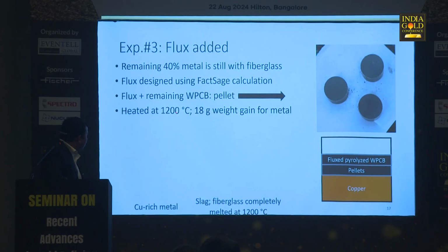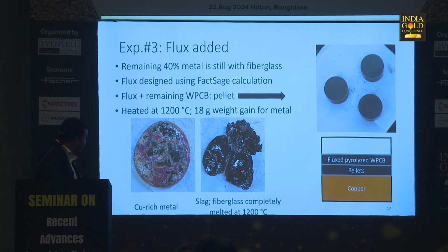Then we processed it at 1200 Celsius only, and after the experiment, you don't have any solid fiberglass left. So you have slag, you have metal separated. This is copper rich metal, and this is slag, and you don't see any fiberglass. So this is the power of those calculations. We didn't have to do trial and error, that we increase this or decrease that, and then do the trials and come up with what works and what does not. These are very robust software and can be used for such calculations.